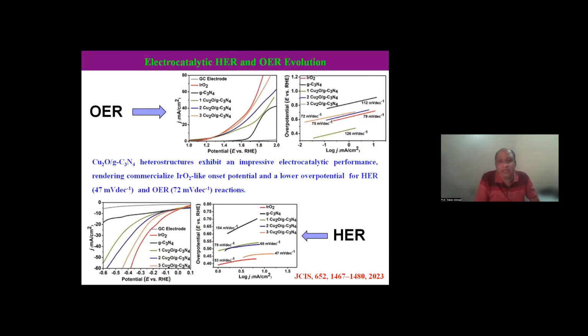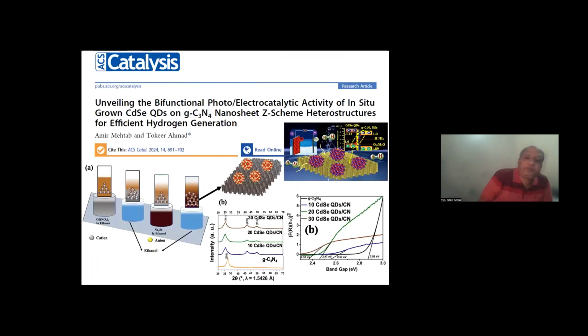And we have added interesting results to the literature when we do the electrochemical HER and OER reactions. We have done the HER and OER investigation and compared all the results with the commercially available iridium oxide electrocatalyst, and we have observed that most of the parameters are comparable or better than the iridium oxide. So we have shown the possibility that the copper oxide nanoparticles with the graphite carbon nitride could be the best replacement for the commercially available iridium oxide.